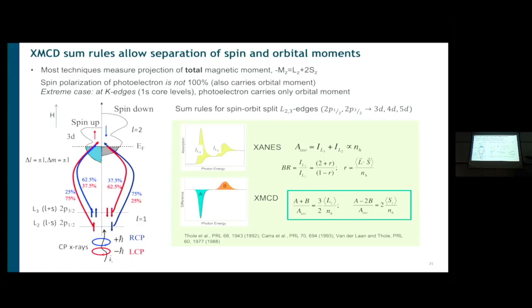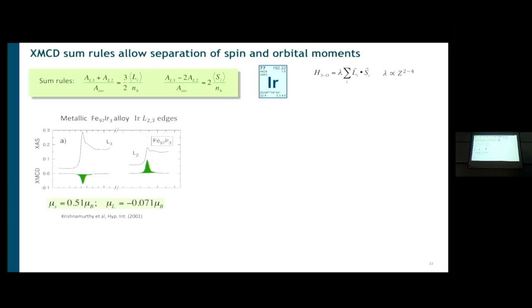So you can see here, if A is equal to minus B, so the L3 and L2 edges, if the areas are equal and opposite, the orbital moment is 0. But if they are different, the orbital moment is not 0. And XMCD means X-ray magnetic charge difference? X-ray magnetic circular dichroism. Oh, I see. Thank you. So here is an example.